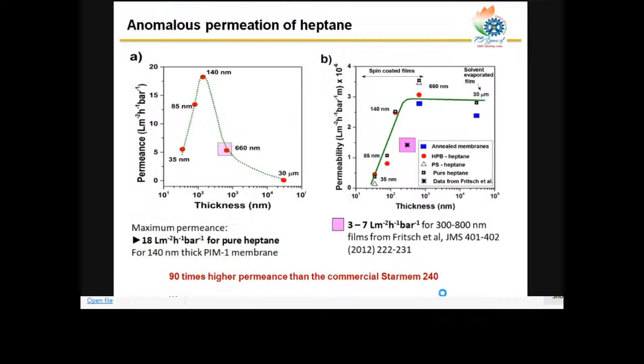With further decreasing thickness, we are actually getting reduced permeance. That was some anomalous behavior. According to Poiseuille's formula, the thinner film should be much more permeable than the thicker one. But in this case, below 140 nanometers, Poiseuille's equation was not valid; the flux was not inversely proportional to the thickness. Why does this happen? Basically your polymer thin film is aging under pressure. The very thin film of 85 nanometers or 35 nanometers is not working, because the intrinsic microporous structures we started with are not available here. The film behaves like a very dense film, and the permeance decreases.